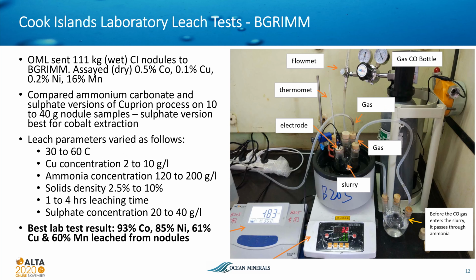A bulk sample of nodules recovered from the Cook Islands, collected in December 2019, was sent to BGRIMM. OML and BGRIMM personnel then worked together to develop and review the testing program. The first tests were aimed at verifying whether the ammonium sulfate process was also better for cobalt extraction on the Cook Island nodules. This was found to be the case. As you can see from the slide, various leaching parameters were then tested. The best laboratory test resulted in 93% cobalt being leached. This was at 30 degrees centigrade and at atmospheric pressure.